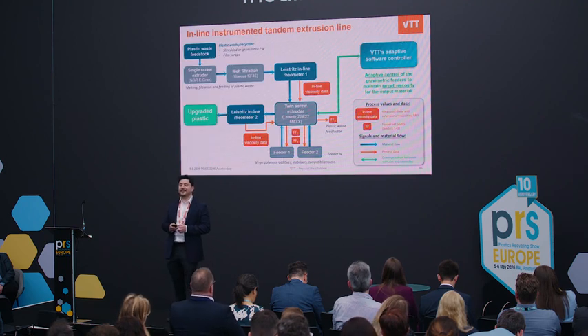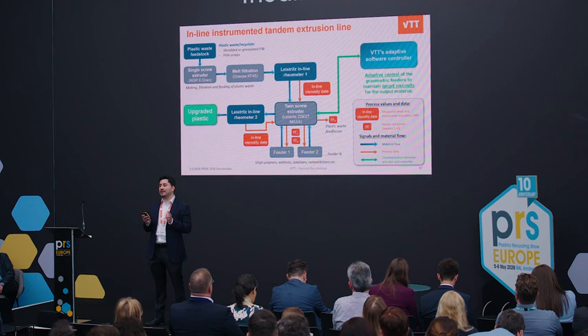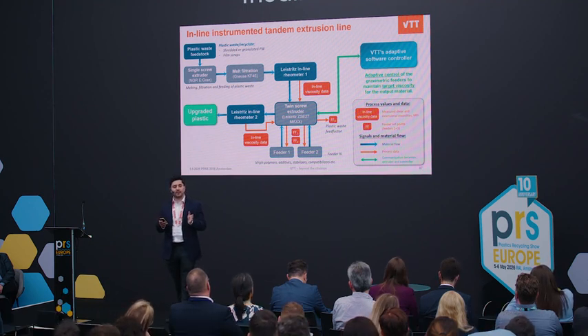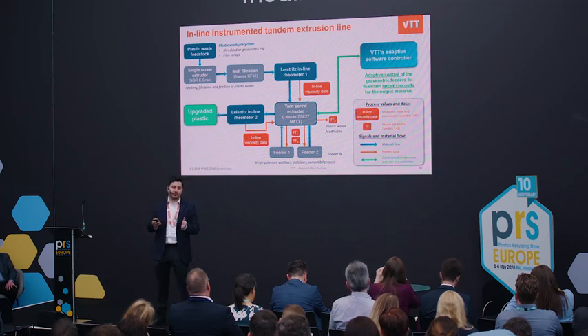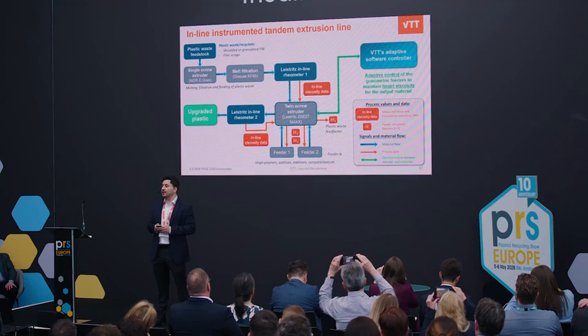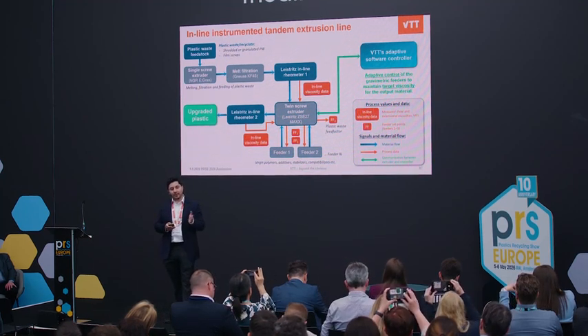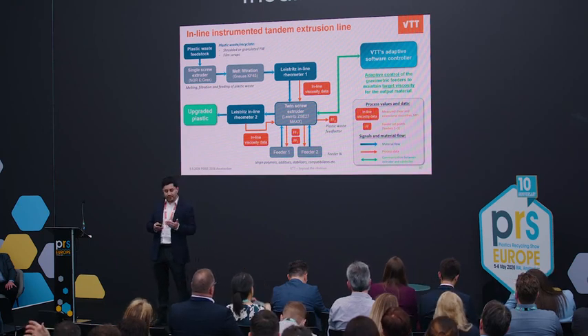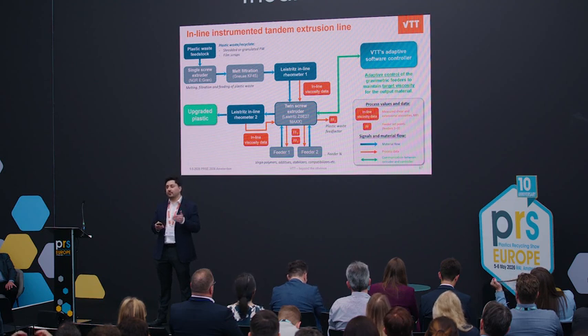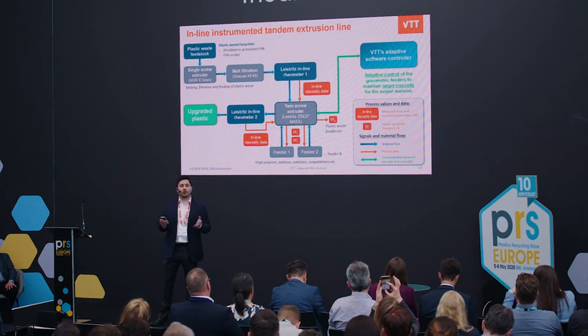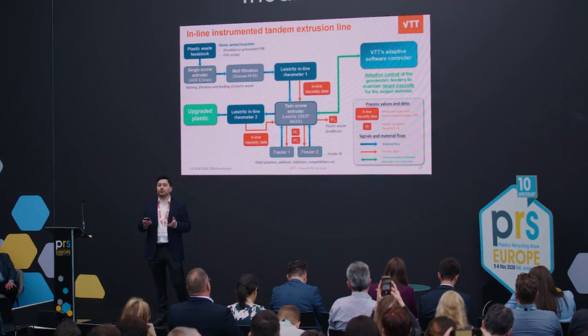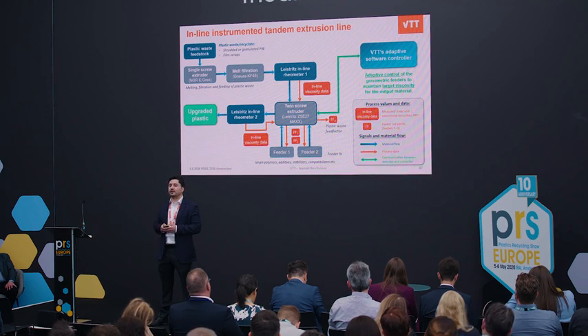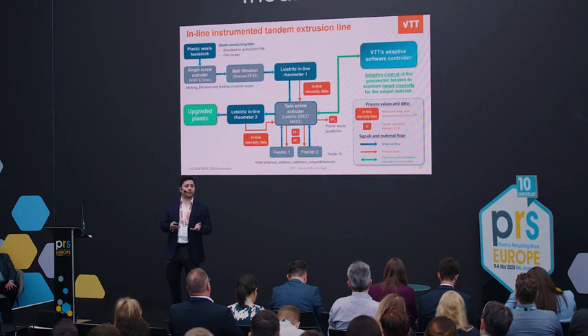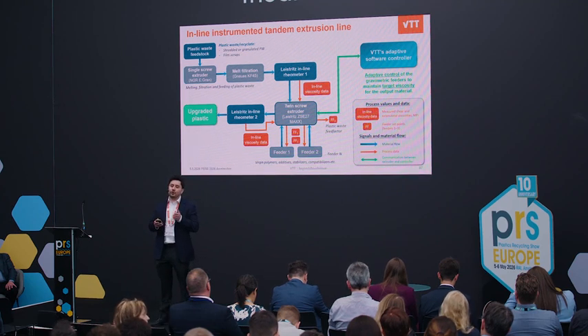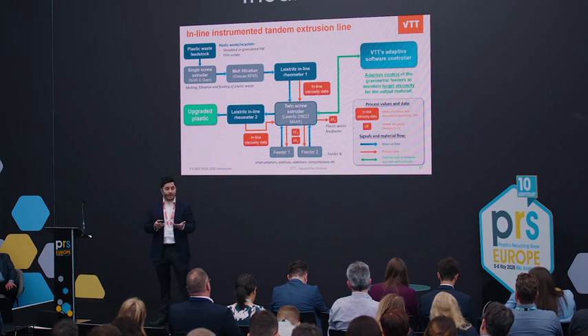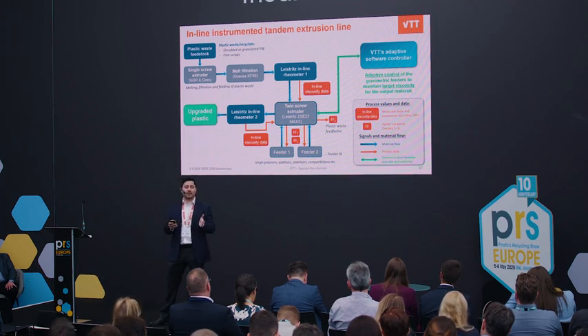But going a bit more technical, what we really do here is we first feed the plastic waste feedstock to a single screw extruder. And here we have the possibility to feed more bulky structures than just granulates. It can be flakes or larger parts like films or even some textiles. And then it goes through melt filtration. Then we measure the viscosity inline continuously, as I mentioned before. And then all the melt is fed to the twin screw extruder, where the compounding really happens. There we are able to feed additives, virgin materials, or several other polymers, for example, that we would like to blend with our main polymer. Towards the end of this twin screw extrusion, we also monitor the rheology again. So we have double viscosity values before and after the actual compounding.